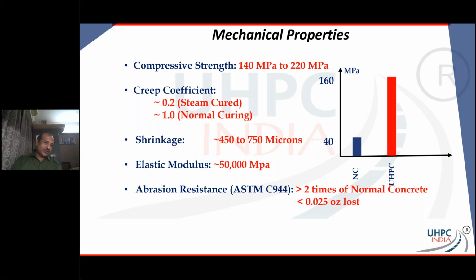I would directly jump to the elastic modulus at this point. Look at the elastic modulus. It's as good as about 50,000 MPa. If you do some tests, you're probably going to get even a little bit more, 52, 54. Believe it or not, people have made UHPC that has shown elastic modulus as high as about 65,000 to 70,000 MPa. So it's a material that can exhibit really great behavior.